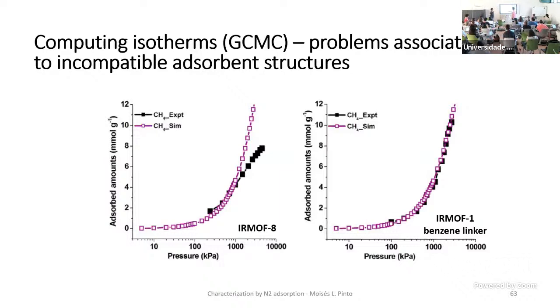Basically, I'm showing it for a material. Moisés found that when he adsorbs, in fact this was done for ethane and ethylene, these gases in a structural model of a MOF, that was IRMOF-8, and we then performed the calculations. We could not compute an isotherm that matched the experimental line. As you can see, not only did the calculated amount differ quite significantly in this material, but also the shape of the isotherm.